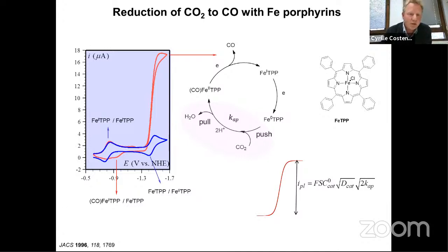no other CO2 reduction product. And actually you can see on the reverse process here that you make CO because CO has a strong affinity with iron 2. And so when you go back here and you reoxidize your catalyst iron 1 into iron 2, this reoxidation is made easier in the presence of CO. This is why this reoxidation wave is shifted in the presence of CO, which is kind of an in situ proof that the product is CO.